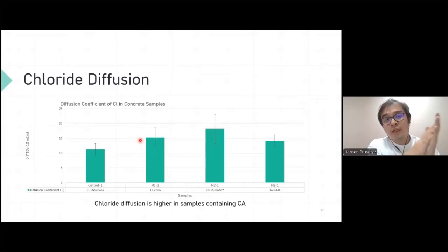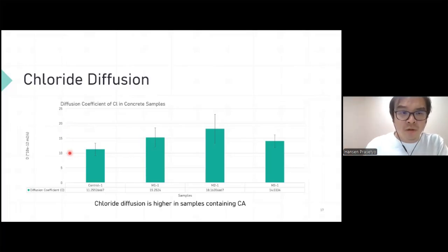We also did chloride diffusion. This also was done by titration. I think this is similar to how Jessie did her test for chloride diffusion, and the apparent diffusion coefficients were also measured using Fick's law.